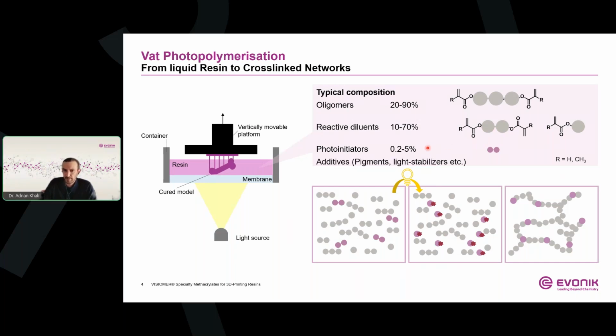We have photoinitiators that basically convert the light energy into reactive species that initiate the polymerization. And finally, we have additives that can contribute to color, stability, processing behavior, or a specific functionality. And through the controlled curing and network formation, the liquid resins are then transformed into highly cross-linked materials, which have tailored properties for different 3D printing applications. And as I mentioned, this process enables the production of highly detailed parts with very good surface quality and dimensional accuracy. And as the final performance of the resin is strongly governed by the choice of reactive diluents, so monofunctional methacrylates and also multifunctional methacrylates, that's exactly why specialty methacrylates can play an important role here.